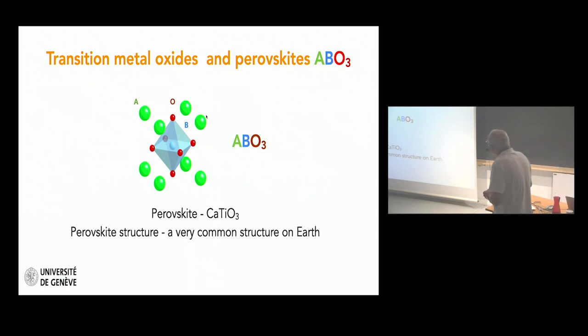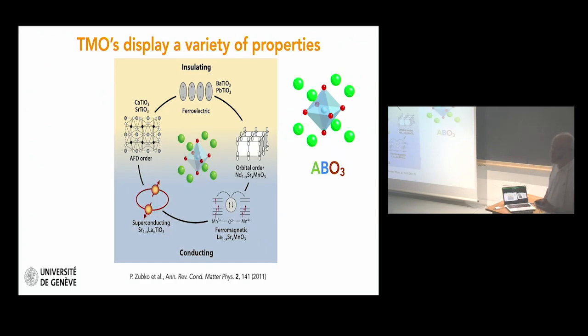Now, why are we interested in these transition metal perovskites? Because these metals display a variety of properties depending on the choice you make for the A and B cations. They can be insulating, they can be conducting, but also they display very many instabilities. Some are structural, I will come back to this in a minute, and some others are electronic. So you see that in this family of materials, you find dielectric or paraelectric insulators like calcium titanate, strontium titanate, but you find ferroelectric materials like barium titanate or lead titanate. You see also systems which display orbital order, magnetism or superconductivity, and all these properties are found in the same family of compounds with the same crystalline structure.